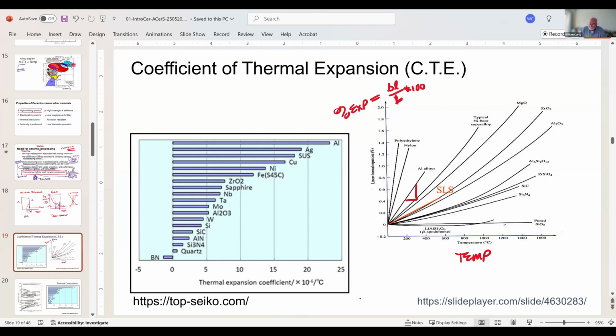So what that means is that I have my sample in a device, and I have a probe that pushes against the sample, and it sits in this tray, and it gets heated, and it measures the change in dimension of that sample as a function of temperature. There's a whole number of things here that are of interest. Polymers and nylon down here: a greater slope means a greater thermal expansion coefficient. So you can see it's a very high expansion coefficient. This is aluminum alloys here. The slopes of these lines are changing dramatically. Magnesium oxide is basically our highest thermal expansion coefficient ceramic.